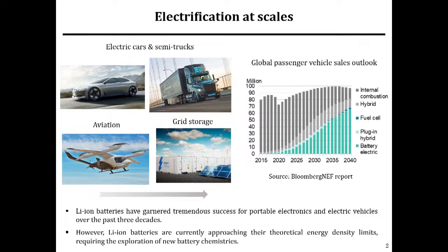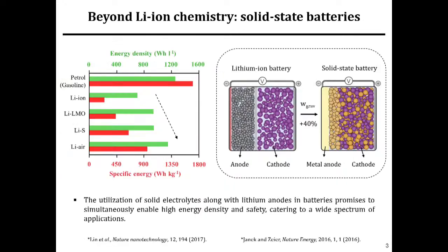Most of these emergent applications require energy densities or power densities significantly greater than what current lithium-ion batteries can offer. In this context, one of the most promising solutions is to replace the graphite electrode in lithium-ion batteries with a lithium metal anode, which has the least electrochemical potential, low weight, and a high specific capacity. As we see in the plot here, replacing graphite with lithium metal provides an intrinsic boost to gravimetric and volumetric energy densities, enabling a wide range of battery chemistries involving lithium sulfur and lithium oxygen, which offer a multifold increase in these energy densities.